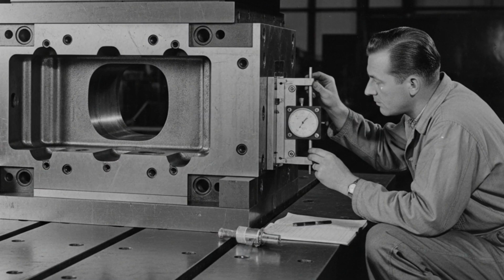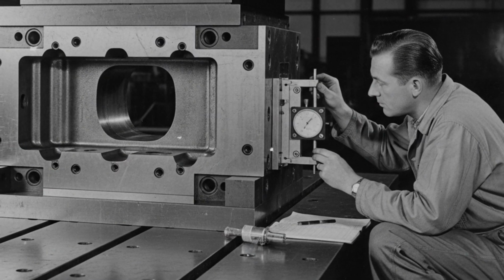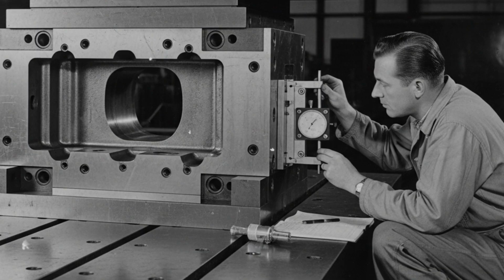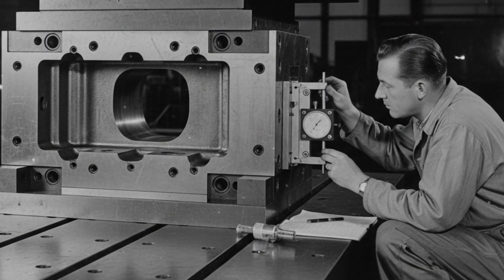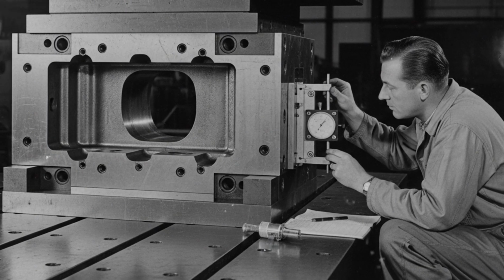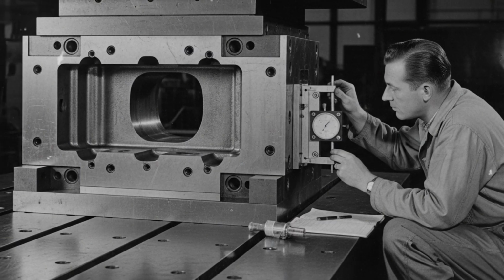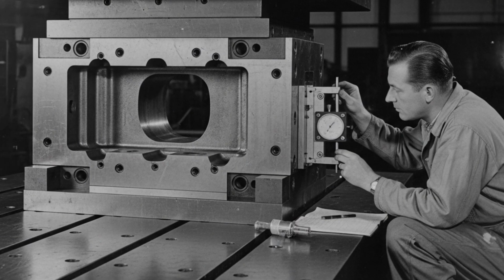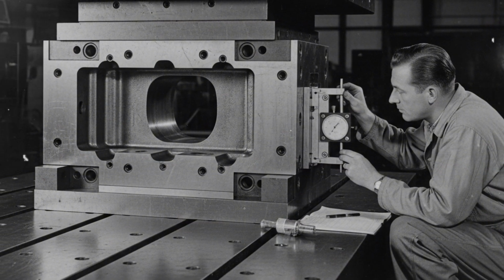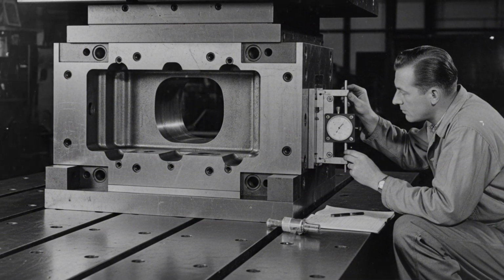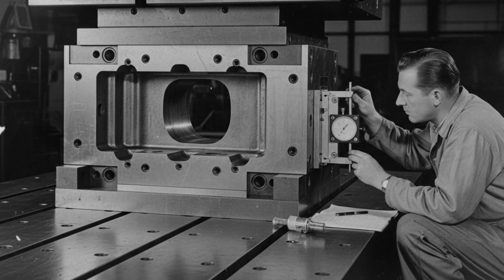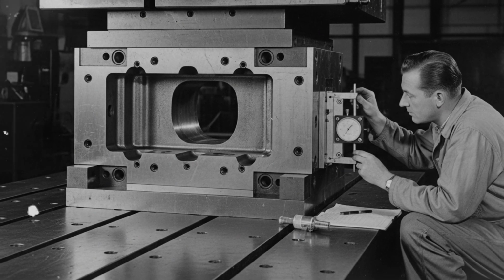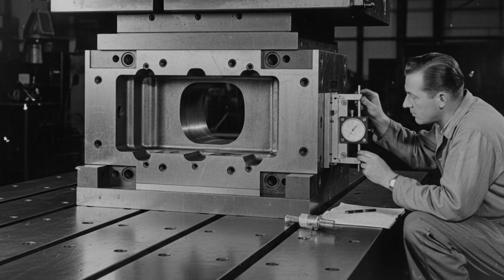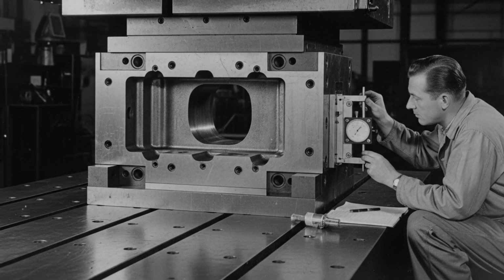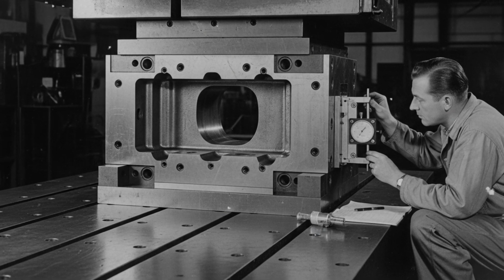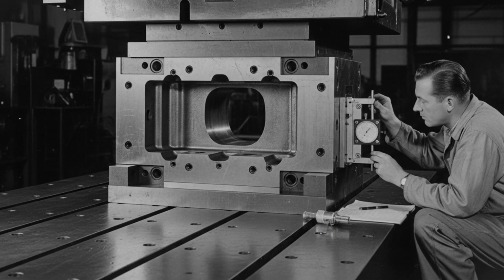The upper die is mounted to the ram face through an intermediate adapter plate, and the alignment between upper and lower dies, measured as the parallelism and concentricity of the matched die cavity surfaces, must be maintained within tolerances of a few thousandths of an inch across the full range of press operation. Any misalignment, whether from thermal distortion, mounting error, or frame deflection, produces a forging with a visible parting line offset that is both a dimensional defect and a stress concentration in the finished part.